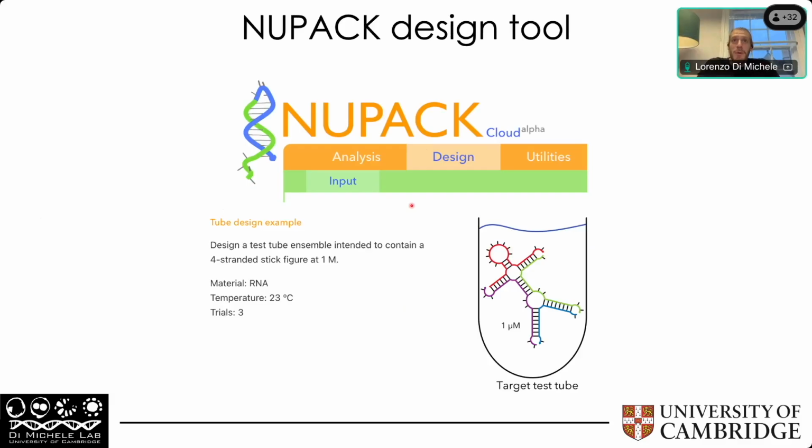Again, advertising NUPACK, because it's a very good one. It has a design tool in which you can specify the shape of the DNA construct that you want to make. For example, this could be a stick figure, and then you tell it, I want my stick figure to be stable at 23 degrees Celsius, 1 molar sodium concentration, and 1 micromolar concentration of my strands. And this tool will tell you the sequences of the DNA molecules that will fold into your stick figure.